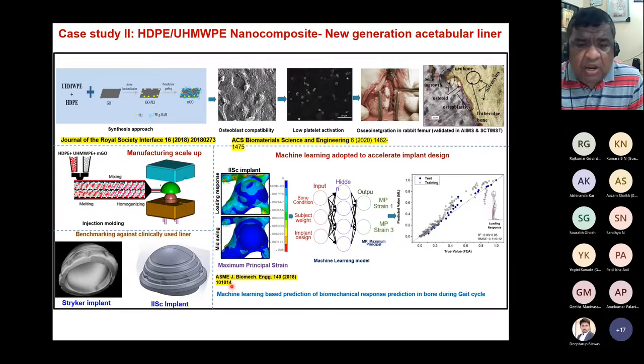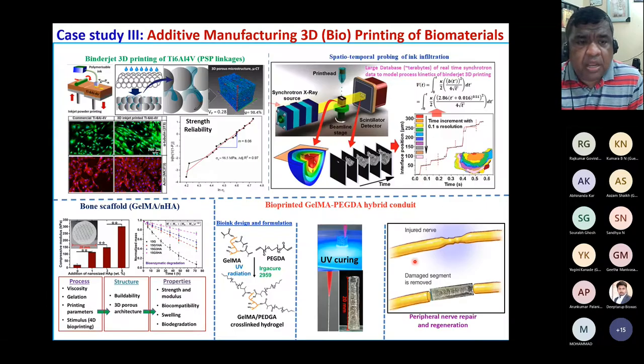This machine learning model takes three different input parameters in terms of the bone condition, subject weight, and implant design. And then the output parameters are essentially maximum principal strain 1 and maximum principal strain 3. What you see on the right-hand side is the predicted value and true value. There is a very significant correlation, with the R-square between the training data and the test data going around 0.93 to 0.95.